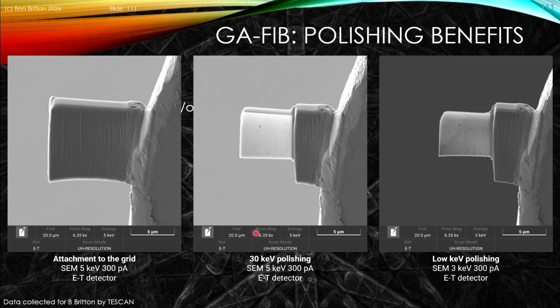So when we see this, and this is a different example that was prepared kindly by colleagues at Tescan, here we can see effectively that the polishing steps are really nice because careful polishing goes from effectively the attachment step. Once you do the polishing nicely, you can get a beautiful example where you see that grain boundary and all the precipitate starting to appear. And here we've effectively gone from 30 kV polishing to a low kV polishing in this example.